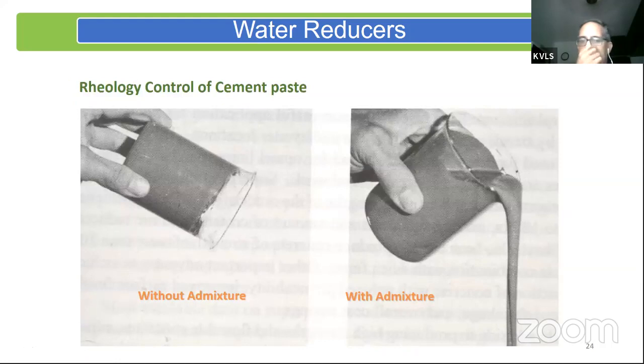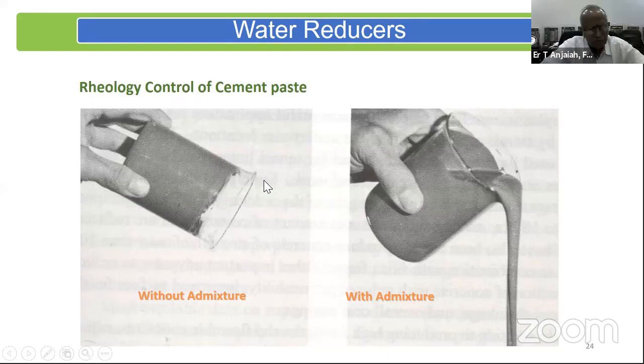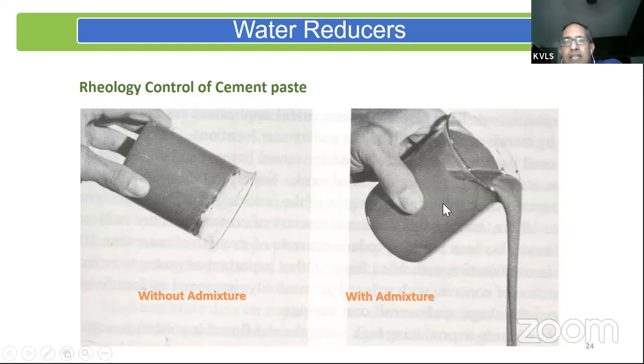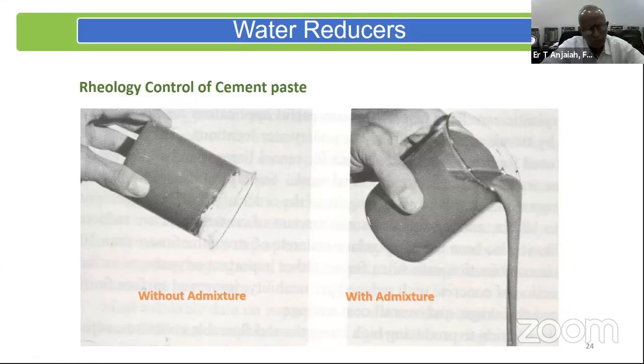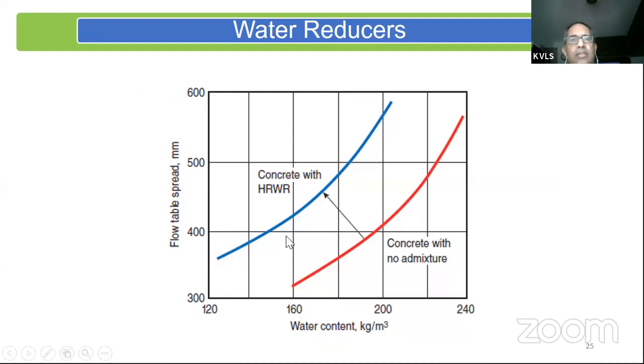And basically, if I look at cement paste without that admixture, it is a paste, but it's a very viscous paste. And I'll have difficulty trying to empty it out of this beaker here. But the minute I add a few drops of this water reducing admixture, I'm able to get it to flow like a very thinly viscous liquid. It starts emptying the container very easily. So this is rheology control, or the flow control, that I'm achieving by adding just a few drops of this water reducer. It's a chemical, and this is basically the role of the water reducer.